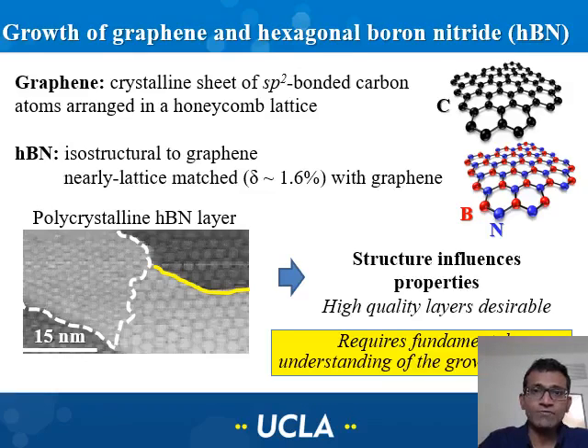As you are probably well aware, graphene and hexagonal boron nitride are probably the most extensively studied materials belonging to this newly established two-dimensional layered crystals. Over the past 15 years, several novel devices have been demonstrated taking advantage of their unique layer thickness dependent properties. With the realization that the properties and hence device characteristics depend sensitively on the layer crystallinity, layer orientation, and thickness, there has been an increased amount of interest in understanding the growth-related aspects associated with these materials. And understanding and controlling the layer quality will require a fundamental insight into the growth-related aspects.